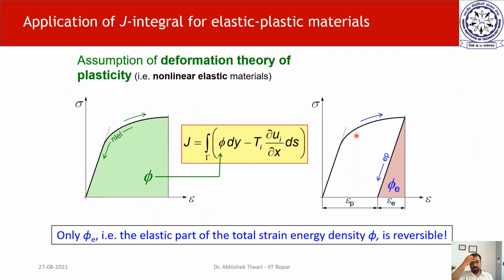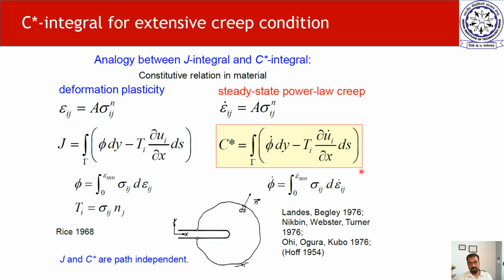The other problem with conventional J integral is that it assumes non-linear elasticity, which means the complete area under the stress strain curve. Although for elastic plastic or elastic creep material, not all energy is available for the crack tip, and plastic energy is not available because that is dissipated, also the creep energy. So only elastic energy is available for the crack tip to grow, and that causes a value which is much away from the true crack driving force of the material for elastic plastic and elastic creep materials. Let us look at what happens when the material is creeping instead of plastically deforming.